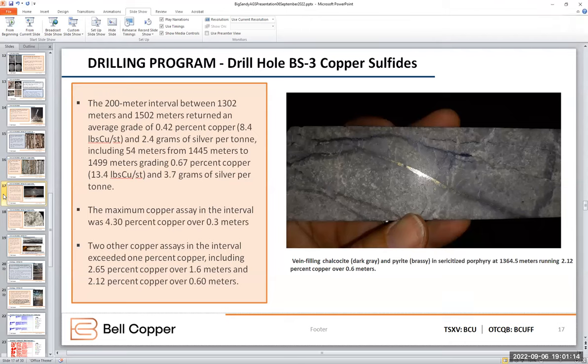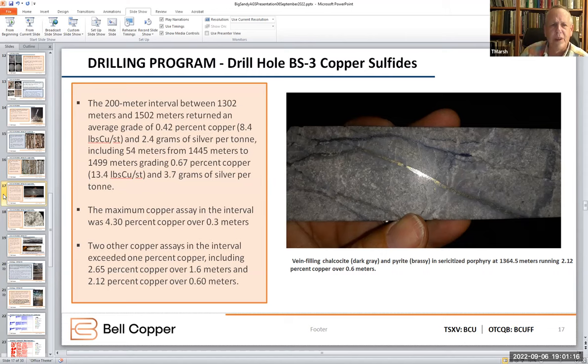All right, so assay results. We cut 200 meters between 1302 and 1502 meters, averaging 0.42% copper, 8.4 pounds per short ton, along with 2.4 grams of silver. And there was a somewhat richer interval of 54 meters, grading 0.67% copper and 3.7 grams of silver.